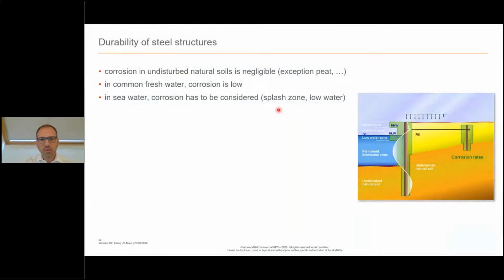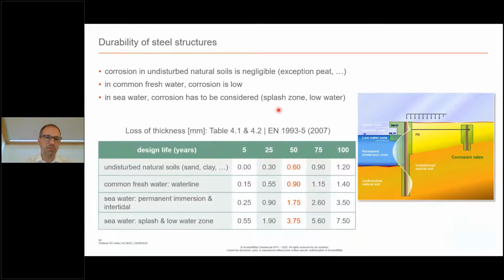Durability doesn't change anything. It's steel, so it corrodes. In undisturbed natural soil, not that much. You can even neglect it. But in seawater, you have to take that into account. Mostly in the splash zone and also in the low water zone. Those are the most aggressive zones that you have. Luckily, the permanent immersion zone, where you have lower corrosion rates, is where you also have the bending moments that are maximum, so the maximum stresses in the steel.